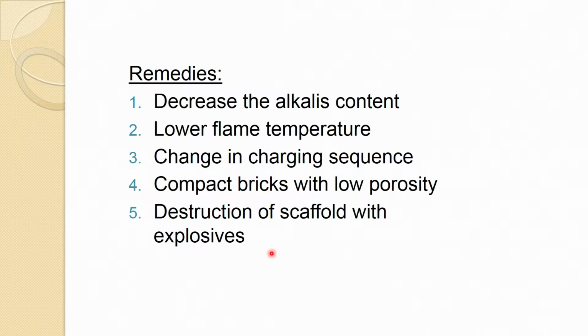So, what are the corrective actions for this? Decrease the alkali content, which comes mostly from the coke, sometimes with some ore. So, low alkali content material must be charged. Lower the flame temperature, because by that alkali is vaporized and then goes up and condenses near that. Change the charging sequence. Use compact bricks with low porosity. The brick lining should be much more compact with a low porosity, so that it cannot be attacked by alkalis, and that softening will not occur.